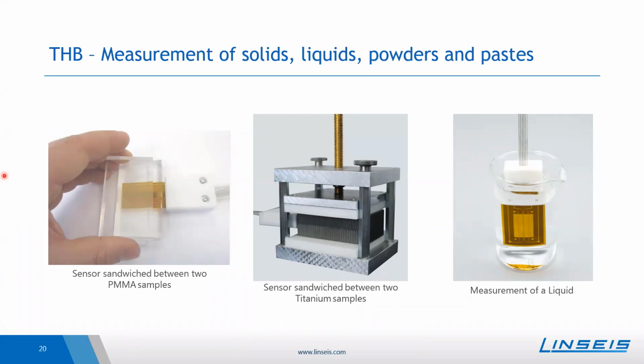And then if one has the sample ready, one just sandwiches the sensor in between those 2 sample pieces so that the sensor foil is completely surrounded by the material. And then one presses the configuration a little bit together. This is done to enhance the thermal contact and reduce the thermal contact resistance between the sensor and the sample. Additionally, one avoids some air in between the 2 samples. So the sample setup is very easy. Sandwich the sensor and the samples, press it together, and that's all.